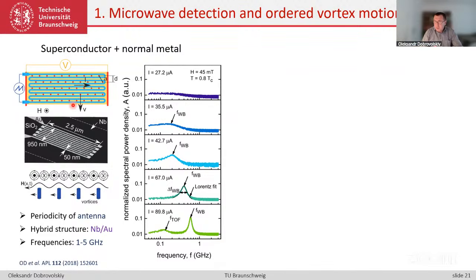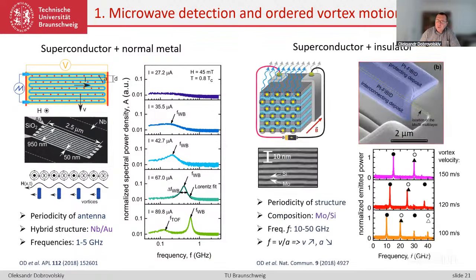So typical frequencies were already in the proper frequency range, the low gigahertz range. And another question was whether some other approach can be used to enhance the periodicity of the vortex structure. So we considered not the periodicity of the antenna, but the periodicity of the structure itself, which was composed of a superlattice of 50 double layers of molybdenum and silicon, with current applied this time in plane, from left to right in the plane of the screen.